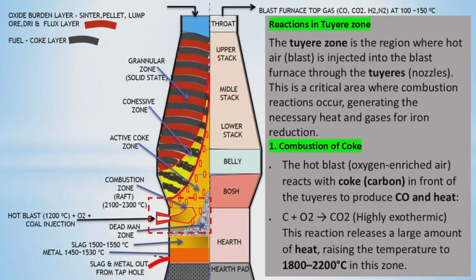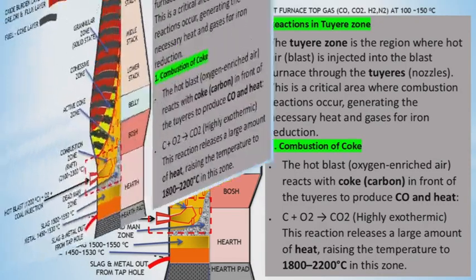Reactions near the tuyeres. The tuyeres zone is the region where hot air, blast, is injected into the blast furnace through the tuyeres. This is a critical area where combustion reactions occur, generating the necessary heat and gases for iron reduction. Combustion of coke, primary reaction. The hot blast, oxygen-enriched air, reacts with coke, carbon, in front of the tuyeres to produce CO and heat. C + O2 = CO2, highly exothermic. This reaction releases a large amount of heat, raising the temperature to 1800 to 2200 degrees Celsius in this zone.